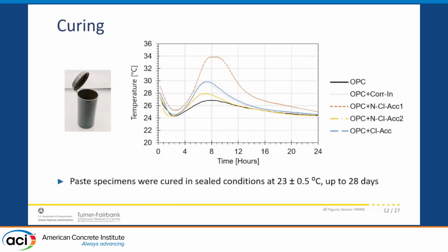The way we cured the specimens for this test was in seal condition. We didn't want the lime water or the moisture to affect the pore solution in one way or another.